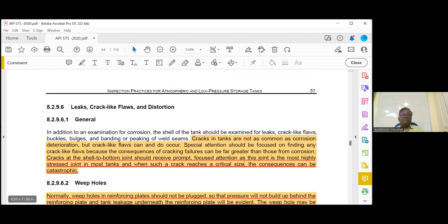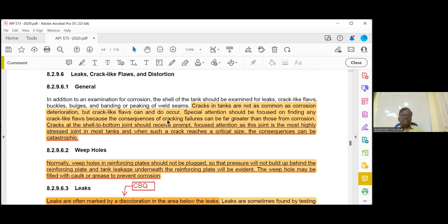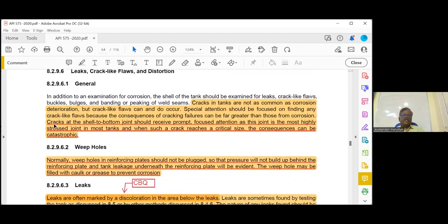Then page number 57. Please go to page number 57. Cracks, the last three lines, 82961. Cracks at the shell to bottom joint should receive prompt focused attention as the joint is the most highly stressed joint in most tanks. And when such a crack reaches a critical size, the consequence can be catastrophic because the complete tank will leak.